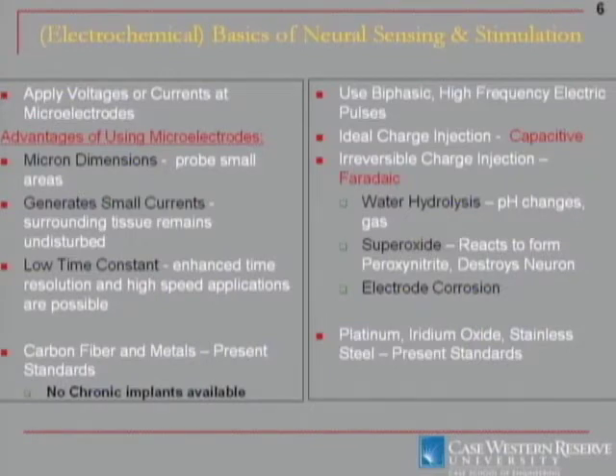From the electrode's perspective, again, this is an electrochemical process. Ideally, we don't want any net species added to our electrolyte, to the tissue. And thus, that charge injection must be a capacitive mechanism that is completely reversible. But there are possible electrochemical reactions called Faradaic charge transfer reactions where species can get introduced or removed from the electrolyte. And these are some examples of those that can happen on metal electrodes. You can break down the water at sufficiently high potentials. Oxygen reduction can produce reactive species, for instance, superoxide. And also the electrode itself can oxidize to form an oxide layer that could weaken the structure. Or in the case of platinum, for instance, at sufficiently positive potentials, you can form chloride salts. So again, electrochemistry is important, and we hope diamond can maybe improve on some aspects as well as help us understand these.